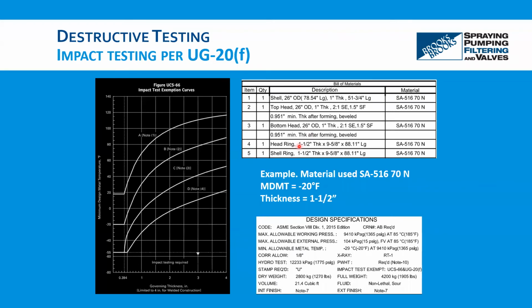we're looking at a thickness here of 1.5 inches. The material used is SA-516-70. This is normalized carbon steel, and the minimum design metal temperature is -20. By following what I mentioned earlier, this design will actually not pass UG-20(f), so we have to move on to UCS-66. Once we do a match based off the thickness and the MDMT, you find you still do not pass. It then leads to other parts of the code where eventually you will find that you are exempt from the impact testing.